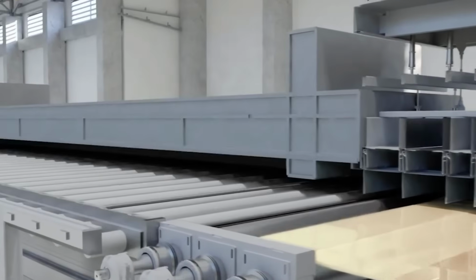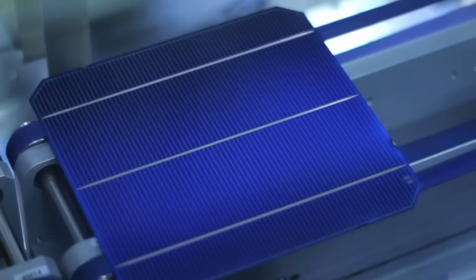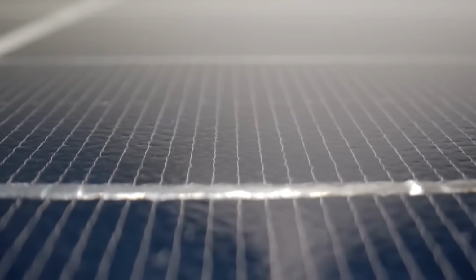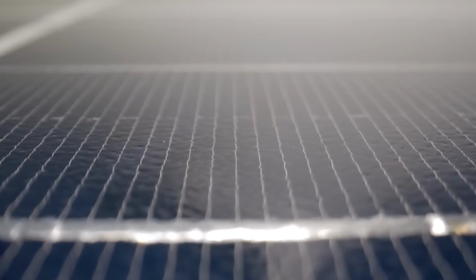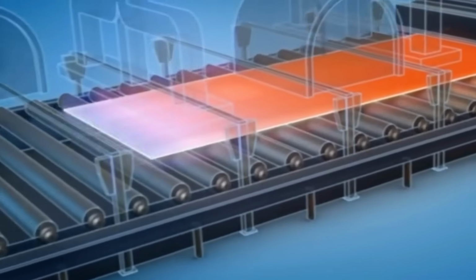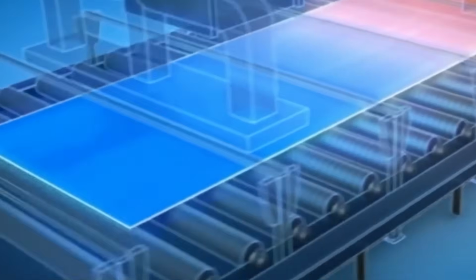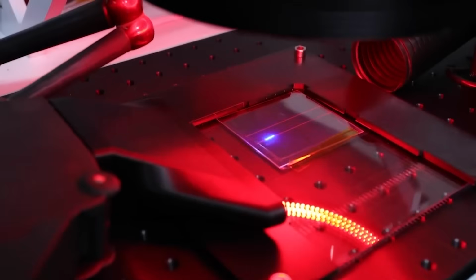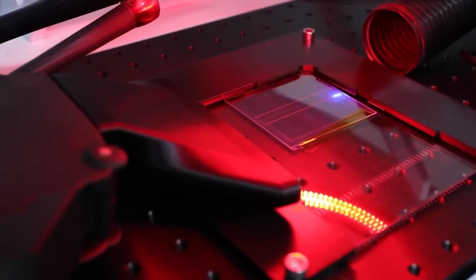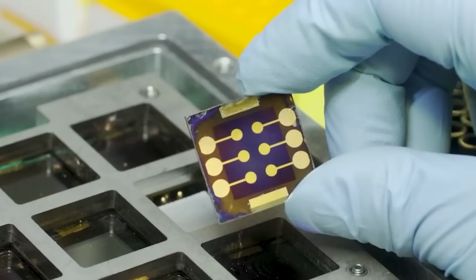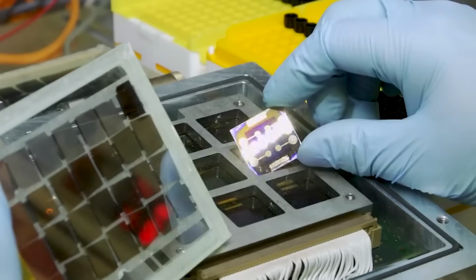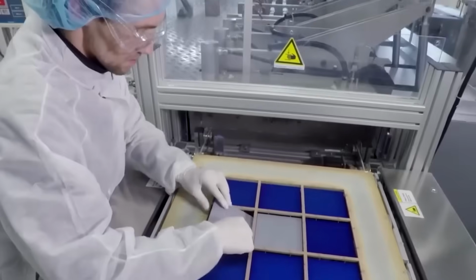The solution that LONGi's materials team developed did not try to escape the curve. It changed what the cell was being asked to absorb. The innovation was a luminescent solar concentrator interlayer, a thin film embedded between the glass lites, formulated from cadmium-free zinc copper indium selenide quantum dots tuned to absorb in the near-infrared and ultraviolet bands, specifically the portions of the solar spectrum that human vision does not use and that building occupants cannot perceive. Instead of competing with the visible spectrum for the same photons, the interlayer intercepted the invisible portions, re-emitted them at wavelengths matched to the cell's peak absorption band, and directed them toward the cell layer via internal reflection. The visible spectrum passed through largely intact.